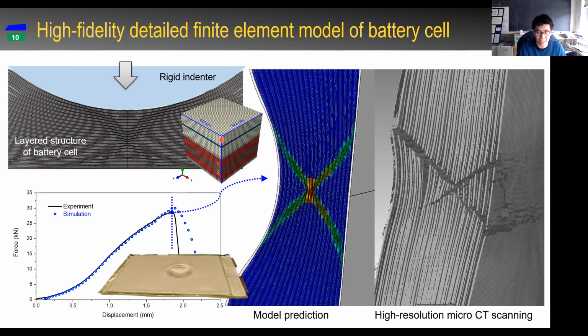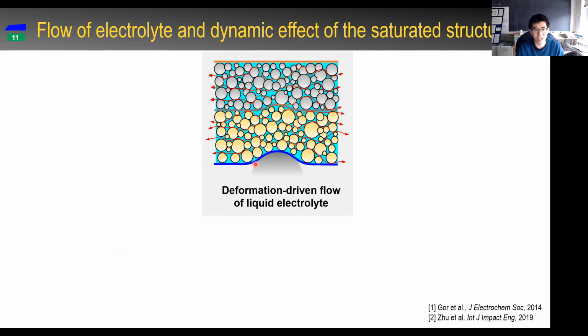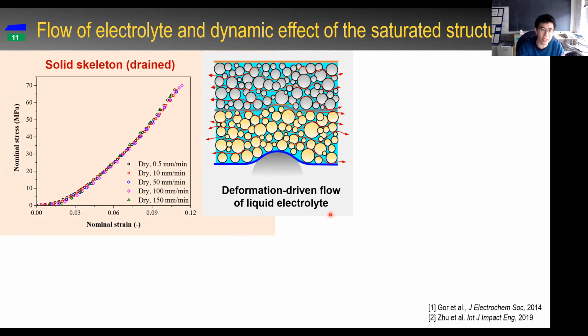That means our solid skeleton mechanics is very well captured, and we are ready to combine this solid skeleton mechanics with other effects, for example, the electrolyte. So what will be the electrolyte contribution? If we do an indentation test, we will see electrolyte being squeezed into the neighboring parts instead of staying in this localized region. So there will definitely be deformation-driven flow of the liquid electrolyte. To validate this effect, we performed several uniaxial compression tests on the solid skeleton. We did five different loading speeds of the compression test on this unit cell, and we measured the nominal stress-strain curve.